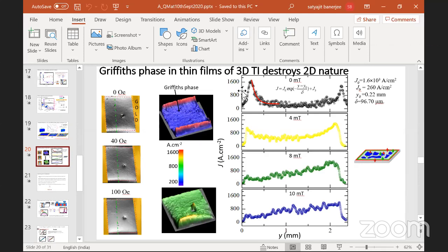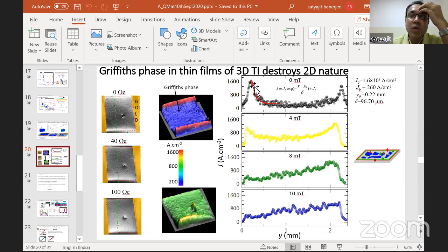if you see the distribution of current, it is not actually one-dimensional. What other people may have missed is that it looks as if there is only current on the edges. There is a lot of current on the edges, but it is also there in the bulk of the sample, in the center of the sample, which is about 200 amps per centimeter square. So it is 2D-like in nature, but it is not a uniform current. It is not a flat-top current. You see large current on the edges, which decreases in the center of the sample. So current is flowing all throughout the surface, but there is more current on the edges than away from the edges. That's what we wanted to mention: you don't have a flat-top uniform current flowing.